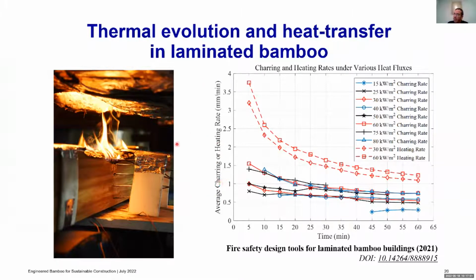The charring rates help us to develop the heat transfer models. You can see here charring rate against time. Charring rate has been a very commonly used property to understand timber performance, and it was definitely key for us to develop the heat transfer models. You can see that the charring rate changes with the different fire exposures and also changes over time. This is particularly important in materials where you don't see char fall off because of the type of glue that we use in laminated bamboo products. We didn't experience much char fall off, which is a very critical situation in timber.